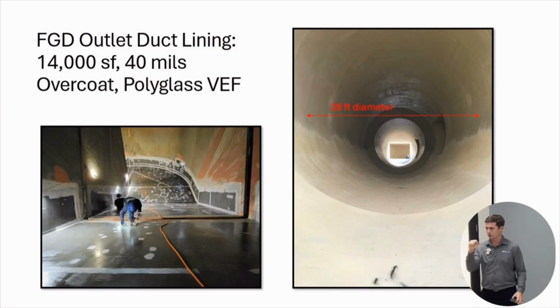So you just kind of sweep blast it to SP7. That's going to expose your weak areas. It'll pop off. If there's holes, you may have a welder that works with us, as we did in this project. They weld that up, and then you overcoat the whole thing. So you put a new film over a swept blast surface that has the profile. Make sense?